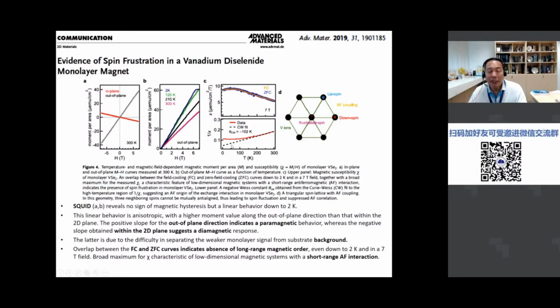So this paper essentially says that in this system, there's evidence of spin frustration. So you can see in this hexagonal diagram here, if this is spin up and spin down, you have a frustrated spin here, which could either be up or down. And these two are anti-ferromagnetically coupled. So that paper questioned the other paper, Nature Nanotech, that this material is intrinsically ferromagnetic.